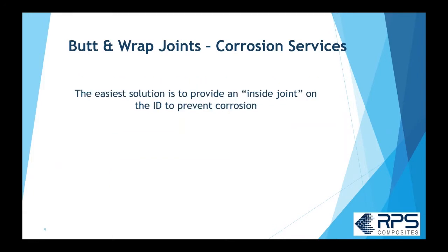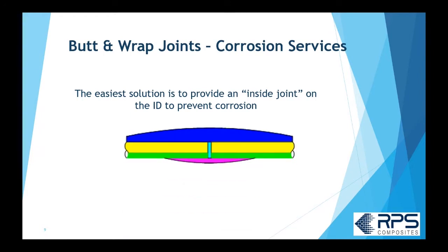The easiest way to prevent that is to use an inside joint. So on the ID of the pipe, you just laminate the corrosion barrier on the ID of the pipe, and that's going to prevent corrosion getting into the crevice space.